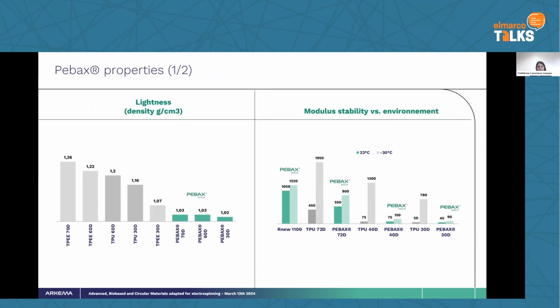In terms of properties, Pebax is definitely very light as well. When you compare to TPU, other TPE, here you can see the gap. On average, Pebax has a density of about 1. And as I said, due to this very low glass transition temperature coming from the polyether, we can ensure a very good stability in very different environments. For example, if you look at the modulus at 23 degrees and -30 on Pebax compared to other TPUs, you see that the gap is lower. With TPU, we can have this rigidification at a much lower temperature, leading to breakage, to a bad durability with TPU.